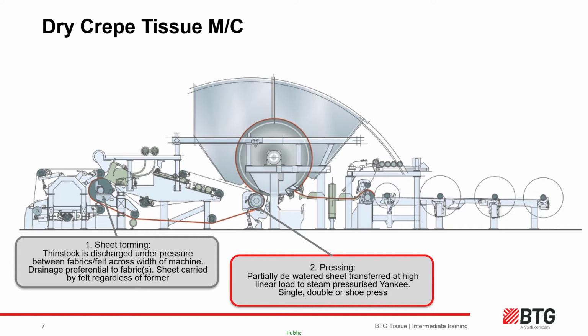Former section drainage would normally dewater thin stock from less than 0.5 consistency to 12 to 15%. Vacuum dewatering on the felt will then increase the consistency to the range of 20 to 25%. Dewatering through the suction press roll will then increase consistency at the press nip to approximately 40%. This is an important consideration for sheet drying energy and for Yankee coating setup.